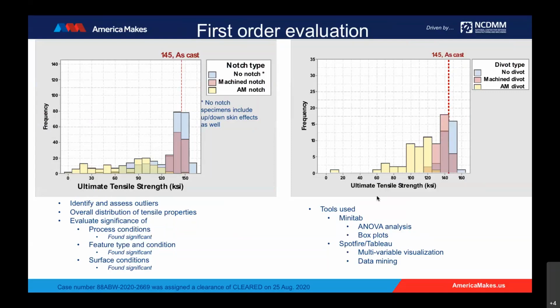so we can understand the effect of having just the machine notch. Similarly, we followed the same logic for divot samples, which is a curvature, a curved cutoff on the coupon. So if you have an AM divot, and a similar geometry machined into the gauge length, which would be a machine divot, and then a specimen with no divot. So if you were to segment the data set from all the different process conditions by these flags: AM notch, machined notch, no notch, AM divot, machine divot, no divot.